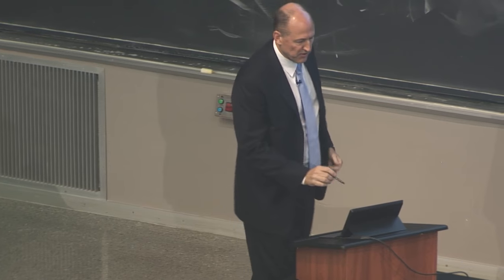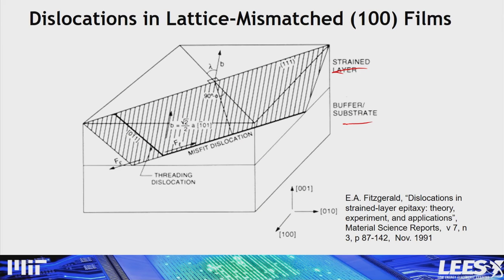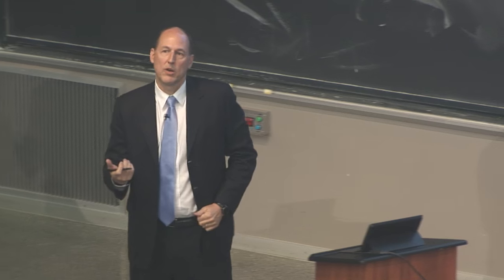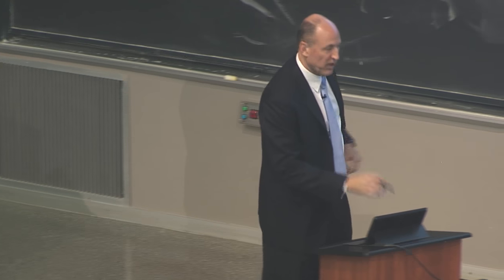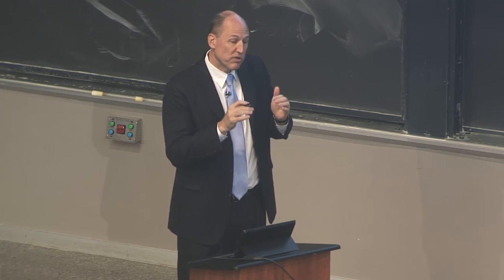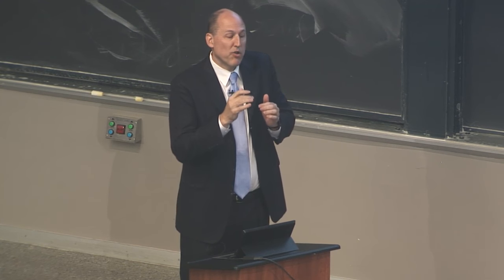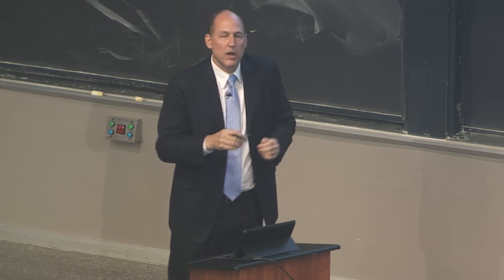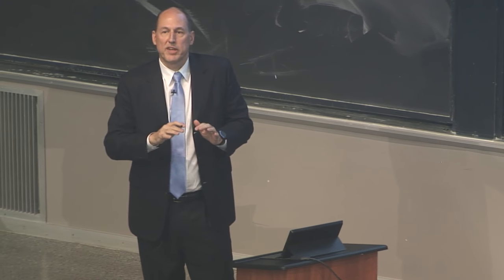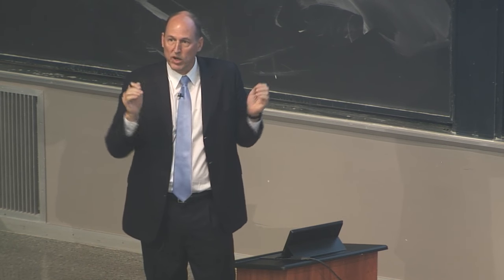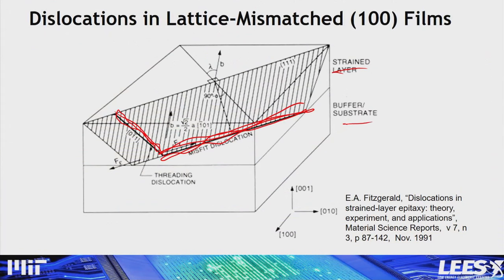And the dynamics of how this comes in become very important. The dislocation sitting at the interface is what allows the layer to relax. And then this dislocation that comes up is a consequence of the fact that a dislocation can't end in a crystal, right? So a lot of times you want to keep it very thin. In that case, you know, okay, I don't want to cross that boundary where dislocations come in. But you're going to see later the big advance is I want it to relax, but I don't want to have many of these things.